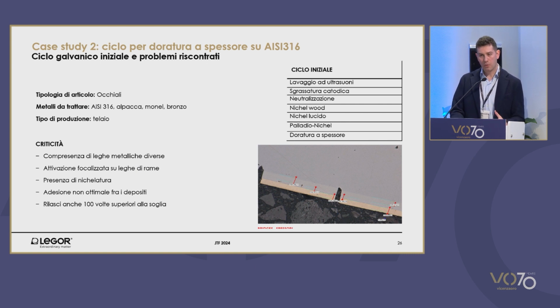It has entrusted Legor with the identification of an electrodeposition process leading to thick layers, 5 microns of a precious metal electrodeposition. The initial cycle is the one that you see depicted here in the slide. Nickel was detected in the electrodeposition cycle. The surface was not activated at best.